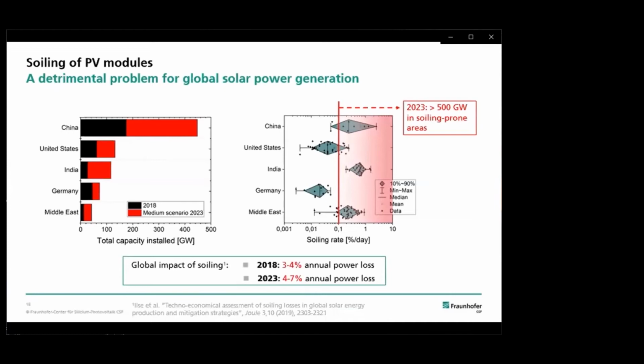From this data, and assuming the economically most optimum cleaning scenarios for the different regions, it follows that in 2018, soiling caused about 3 to 4% annual power loss globally, which is expected to increase to 4 to 7% by 2023 because of the high installation rates in the air polluted areas, such as the desert areas of the Middle East. This makes soiling a severe problem for our future energy generation.